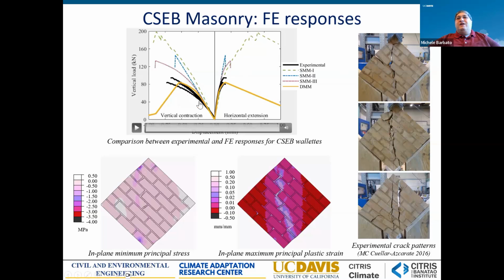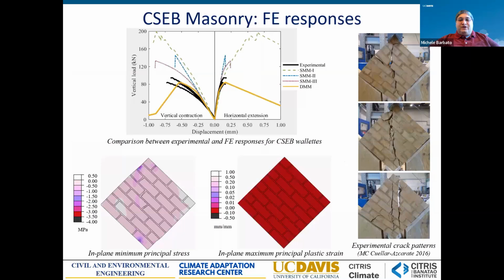This is the yellow line corresponding to this new modeling, as well as the principal stresses and the principal plastic strain in the wallette, where the light color corresponds to where the cracking is developed. You can see that even visually there is a very good correspondence with the experimental results. So as a conclusion, this type of modeling, although more expensive, is necessary in order to capture the real mechanical behavior of earthen construction.